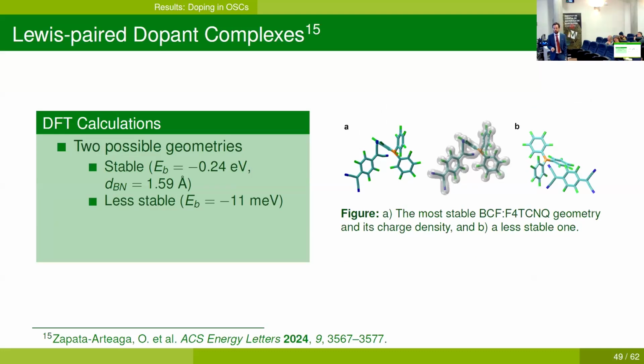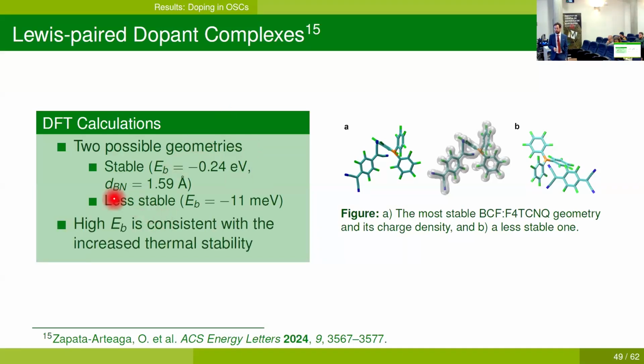So my contribution to this study was minor. We performed DFT calculations to see how the F4TCNQ and BCF complex forms, and also to estimate the binding energy of this complex and its bonding distance. So this is what we found. Actually, we found two different geometries, configurations, one in A and one in B, but B is actually very unstable since the binding energy is minus 11 millielectron volts. The one that we are interested in is this one, and it gives minus 0.24 electron volts and a distance of approximately 1.6 angstrom. The high binding energy that we found is consistent with the increased thermal stability.